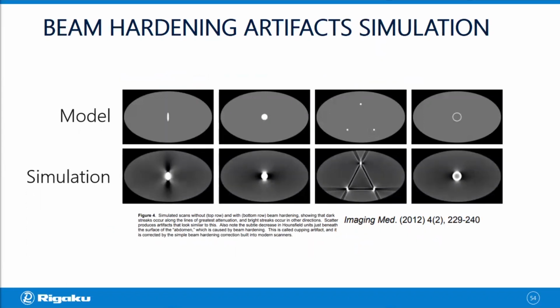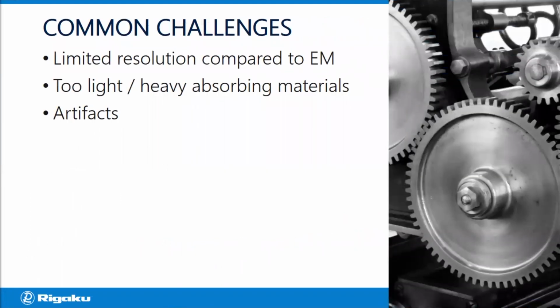You can see that the model and the simulation look different, and that's because the simulation has artifacts, like those streaks coming from the high density areas. It gets worse when you have multiple high density areas, and you see shading like this one sometimes as well. So this is how beam hardening artifacts usually look. And to reduce it, you can always increase the X-ray energy to reduce the beam hardening, but sometimes it's difficult to completely eliminate it. So those are the common limitations and challenges of the X-ray CT technique.